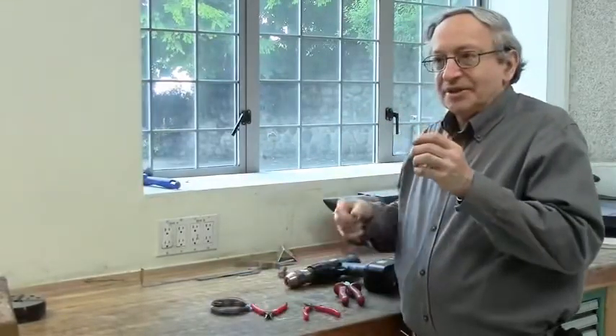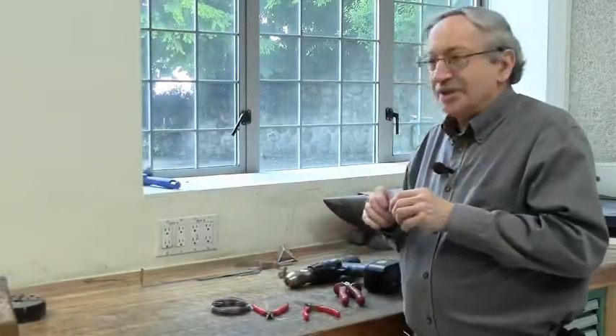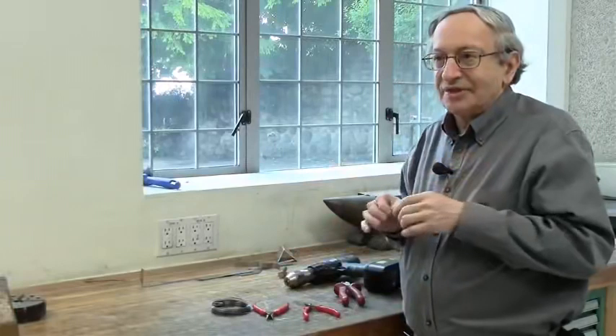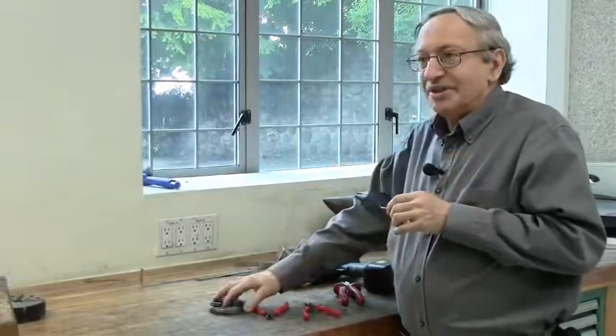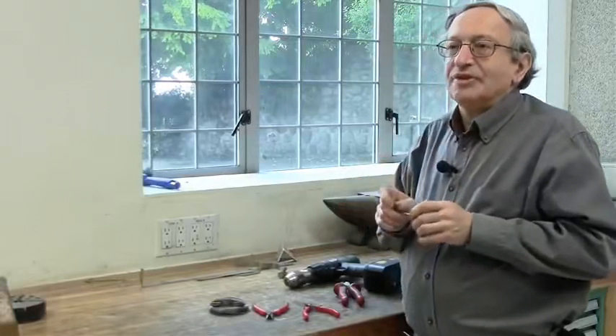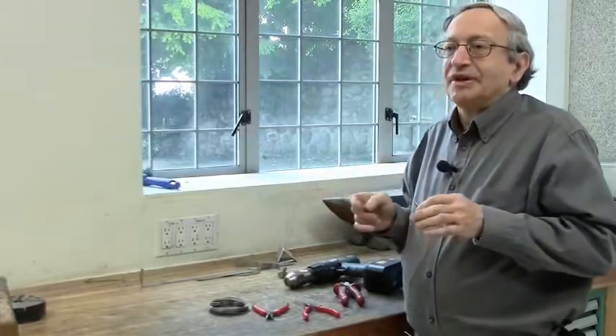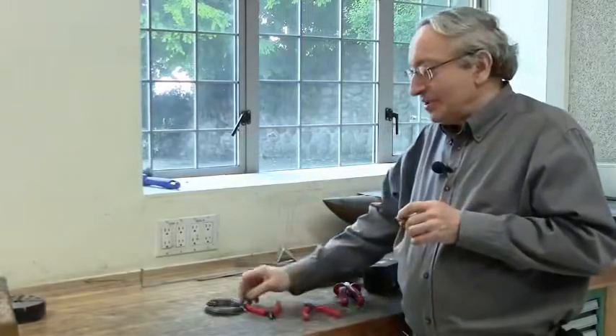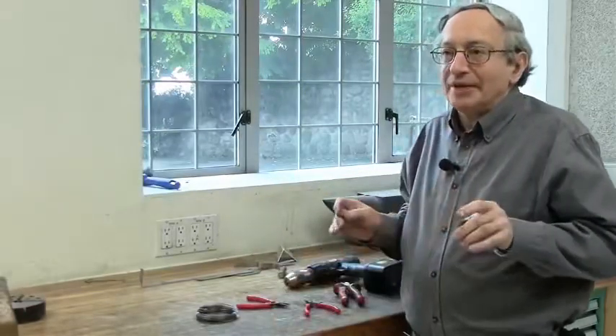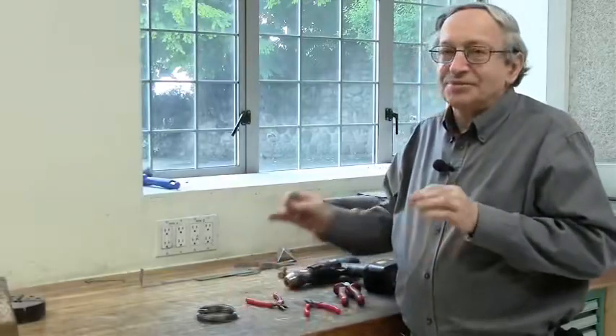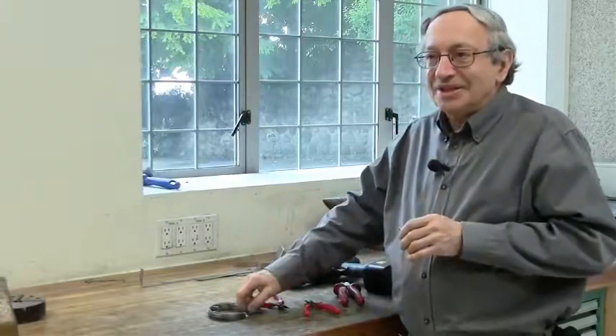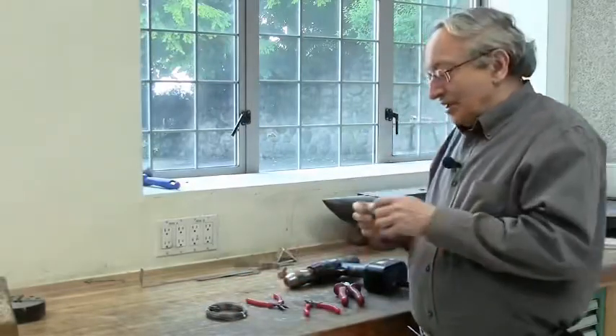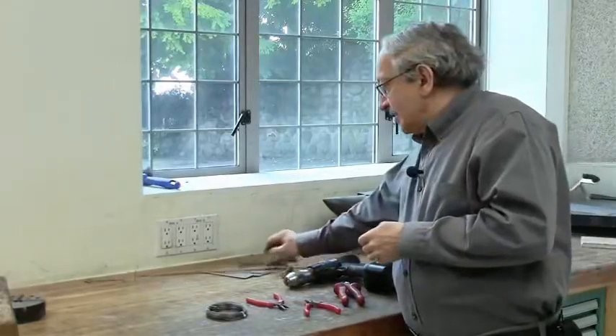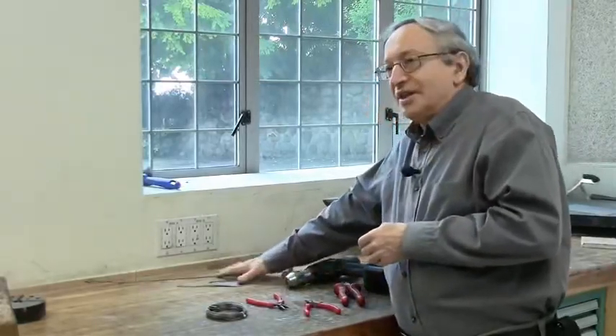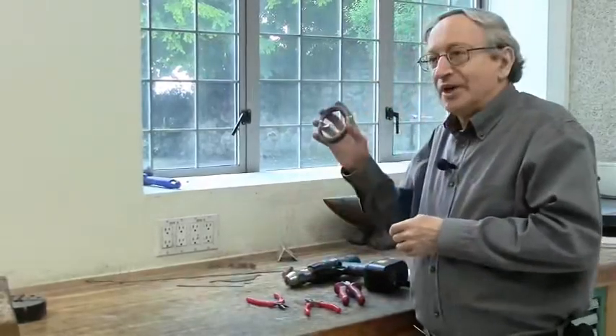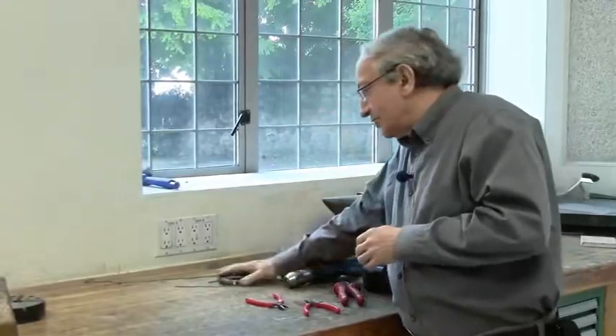You wind the spring. Now this wire, when it's wire, only needs one heating cycle, not two, because it's slightly different metallurgically. So it's already pre-treated. So once you've made the spring, you put it in the oven according to manufacturer's instructions. Typically, for this wire, it's 480 degrees Celsius for 1 hour. But always follow manufacturer's instructions because of different tempers, and the temper or the annealing determines the heat cycle. Okay, so basically 3 types of stainless plus the same alloy in wire, the 17-7, and that's all you need.